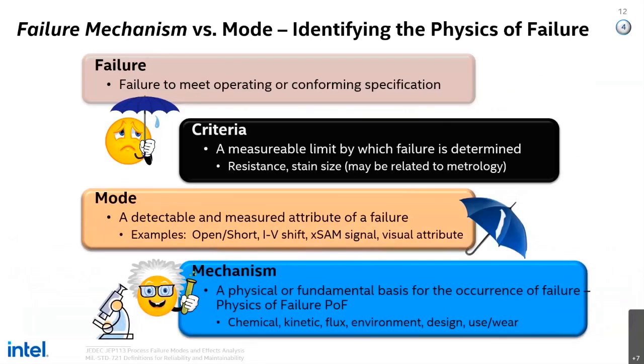Okay, so the next thing is the failure mode and mechanism, and we'll just spend a few minutes here. Failure is essentially the failure to meet an operating or conforming spec. It's detected by a mode. So when we do testing, we're looking for things: opens and shorts and IV shifts, insertion loss, for instance, or visual attributes. From those tests, there may be a resistance or a parametric value that shifts. We may then extract the mechanism, which is the physics. What is the driving energy for failure? And that driving energy can be chemical related, a flux, or a field related type of energy that you're going to look at. And we'll speak to some of those, but this mechanism is key.